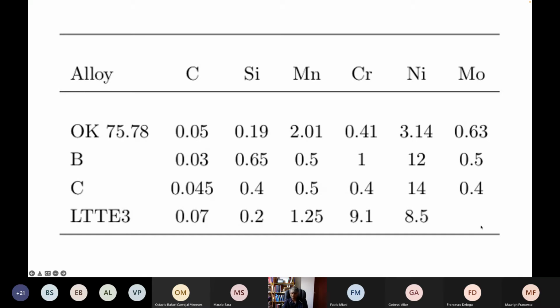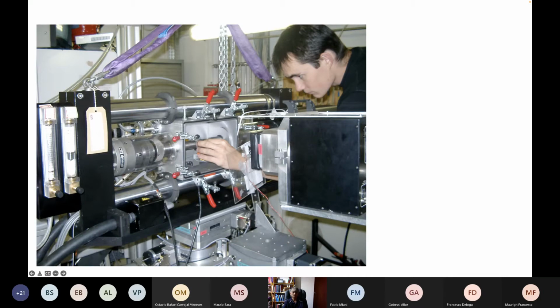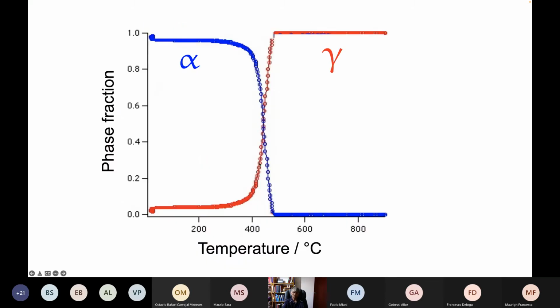So we designed these three alloys and decided to repeat the Albury and Jones type experiment, but this time also using X-ray diffraction to follow the phase transformations and various other features of the behavior as the material cools. So this is effectively a dilatometer that is attached to a beamline at Grenoble. So there are high energy X-rays coming out from here. And this is our sample positioned inside the dilatometer. And we can monitor everything that happens, the stress, all the information from the high energy X-rays and so on, as the cooling happens. So it's straightforward from X-ray diffraction to calculate how much austenite you get and how much ferritic transformation products you get as the material cools, quantitatively.